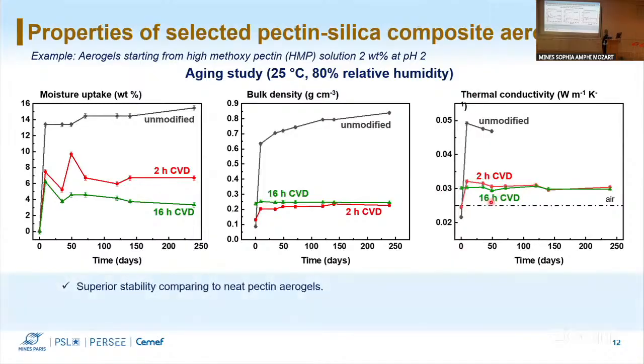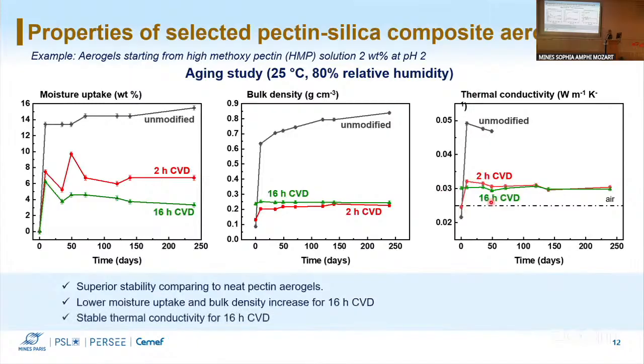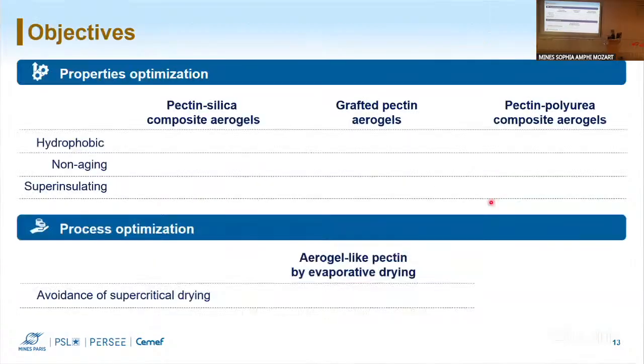So in general, we saw that for the composite materials, we have better stability, and we have lower moisture uptake and density increase when we have a longer deposition time. And for 16 hours chemical vapor deposition, we have stable thermal conductivity. However, we're not in the superinsulating area. Coming back to our objectives, for the properties optimization, we wanted to obtain hydrophobic, non-aging, and superinsulating materials. And for the pectin silica composites, we were able to achieve the first two goals, but not to get the superinsulating properties.